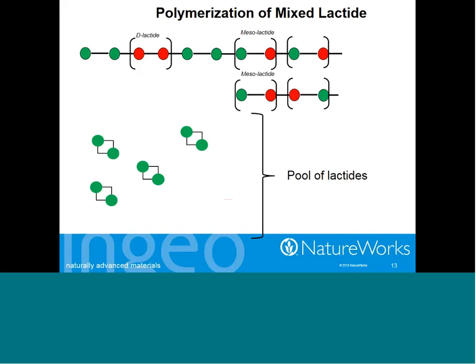And depending on the polymer that we're making, we will have more or less of that material present, and sometimes those molecules have a probability of ending up adjacent to one another, and they can go in either orientation, either in this top screen, which is what I would say is head-to-head, or in the bottom configuration, which would be head-to-tail.